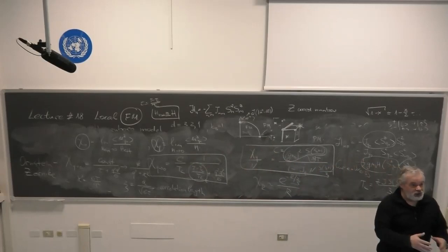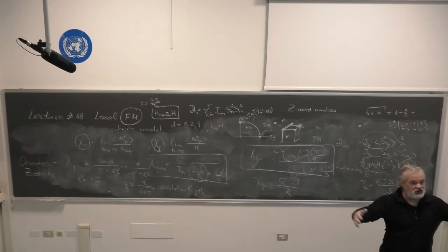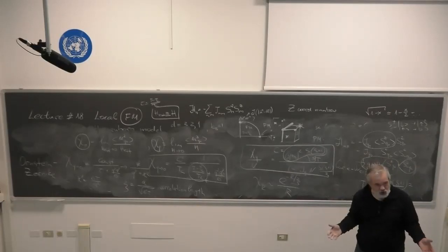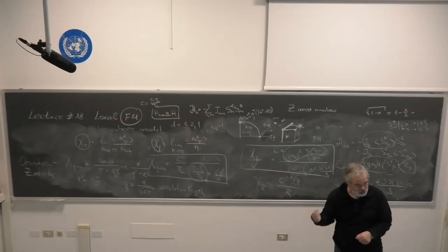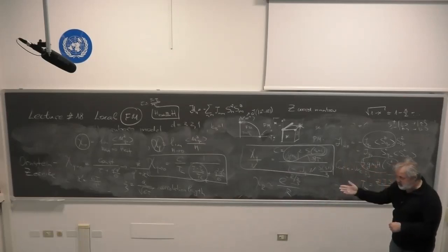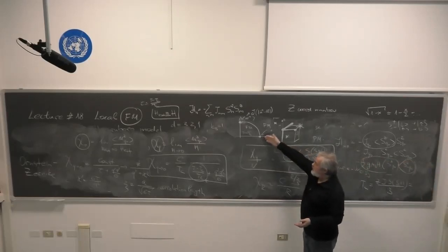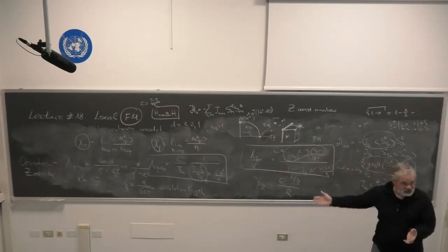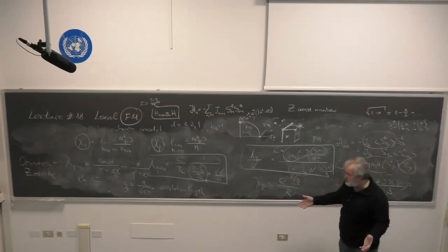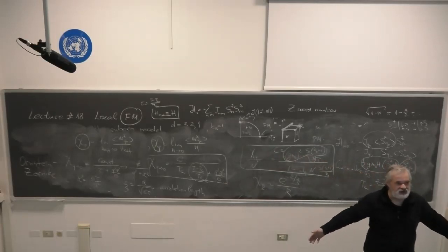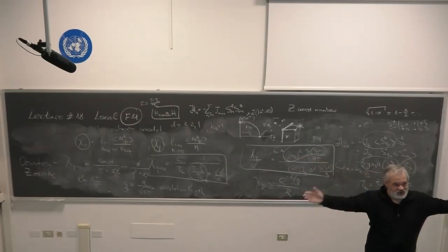is going to be. So when you approach the critical temperature in such a way that your correlation length becomes comparable with the size of the system, the long range order is established. So this is the mechanism of establishing the long range order in the system when you approach the second order phase transition point from above. So this is the meaning of this exercise. Okay, if you deviate slightly from the temperature, then you have only short range orders. Some spins are correlated, but the correlation length is very much limited. Only when you come closer to the phase transition point, actually all spins fill the area of the size of the correlation length.